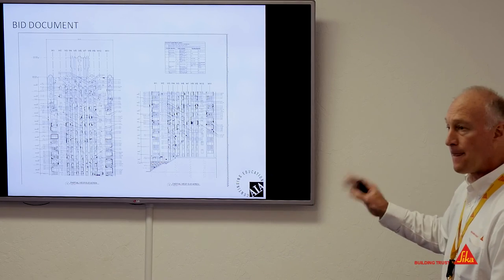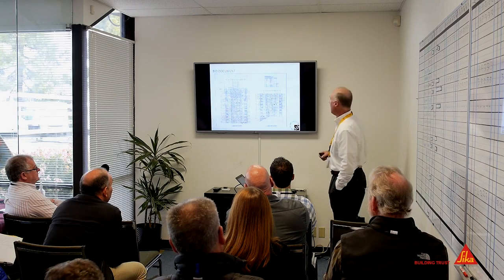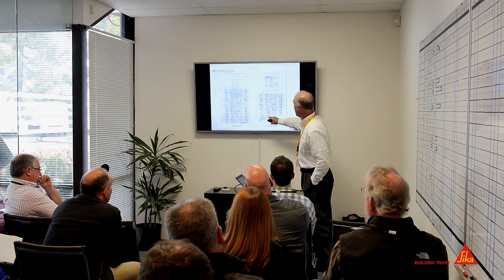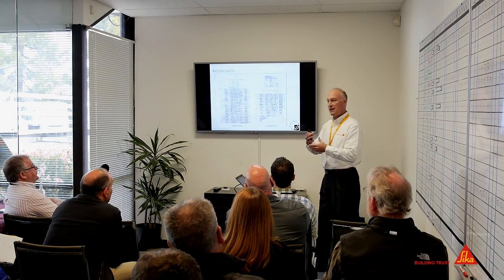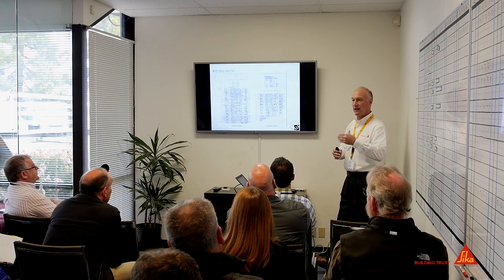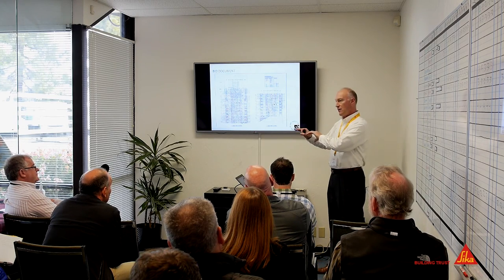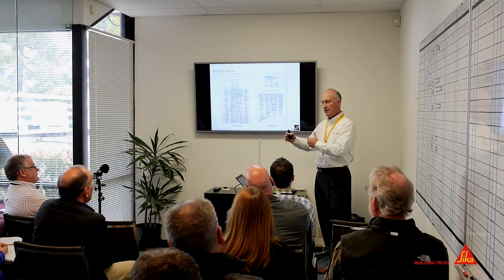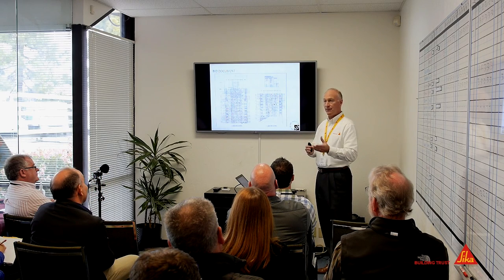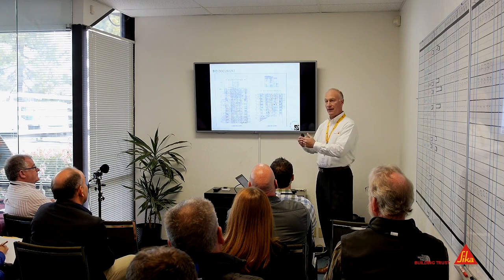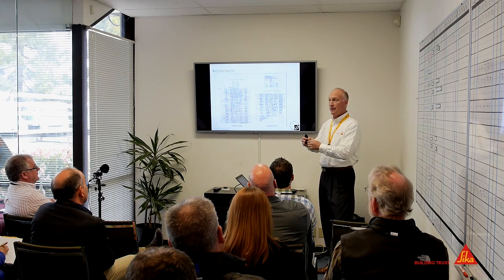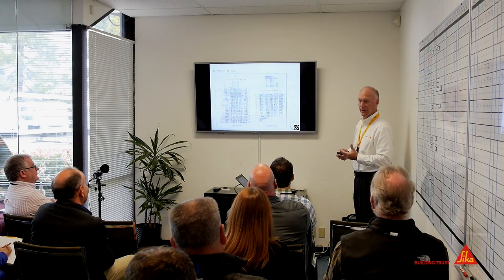So they have quantities by repair type? Yeah, they did identify, around the windows, they tended to be deeper spalls, and I think they labeled them as type A. Within the walls, they weren't quite as deep, and those were type B. So type A may have been 3 inches deep, type B was 1.5 inches deep. But they had an idea of the quantities involved as well.